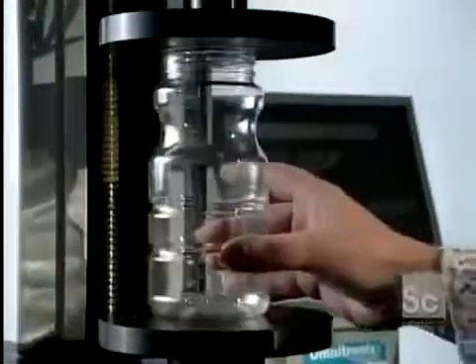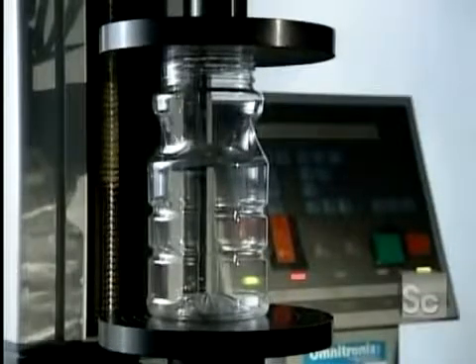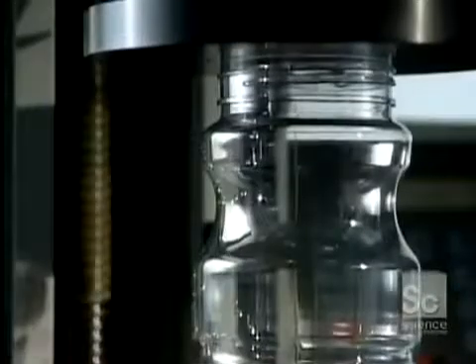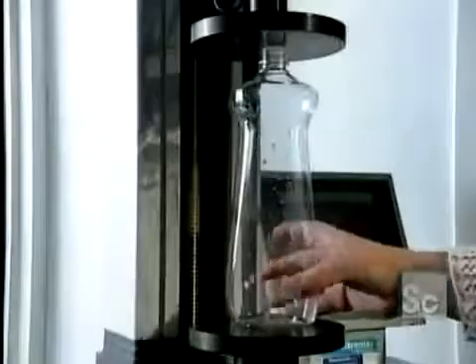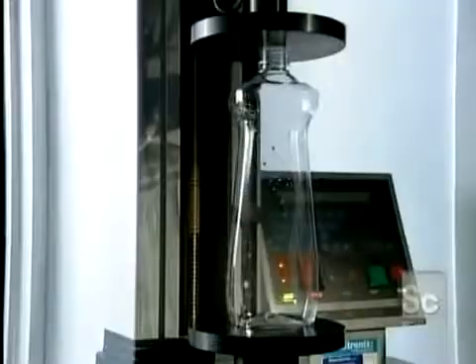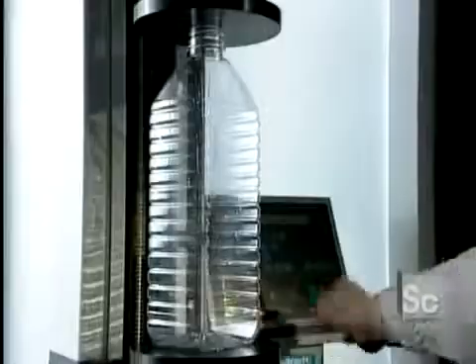The factory pulls samples off the line at regular intervals for quality control testing. Technicians measure the thickness of the plastic and perform a compression test to gauge its strength. They verify the sample's dimensions and capacity. They also evaluate resistance to vacuum pressure, because containers are often vacuum sealed after filling. Some models must also be strong enough to resist the pressure of their contents — carbonated soft drinks, for instance.